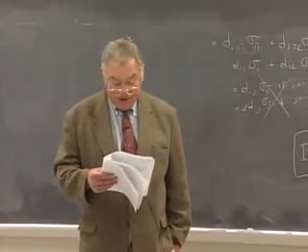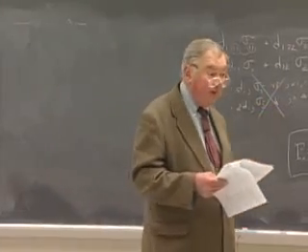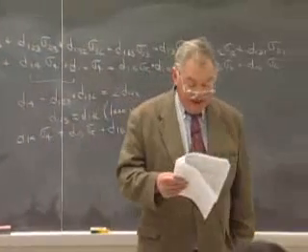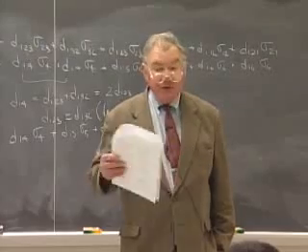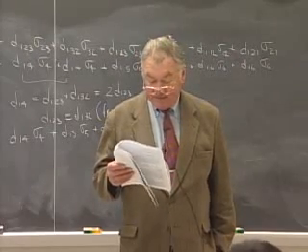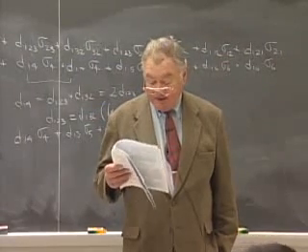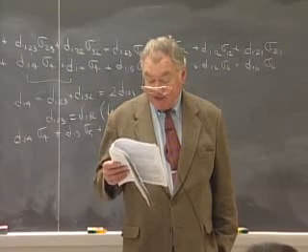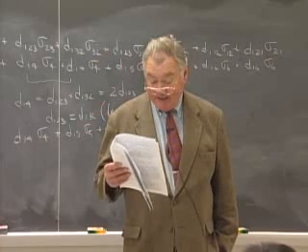These transformations show that no third-rank tensor property can exist in a crystal that has inversion. So the 11 Laue groups, so-called, that possess inversion have absolutely no property and cannot be considered further for third-rank properties. And then one must consider all of the 32 minus 11, 21 point groups that lack inversion separately. There's no reason why they should behave the same way.